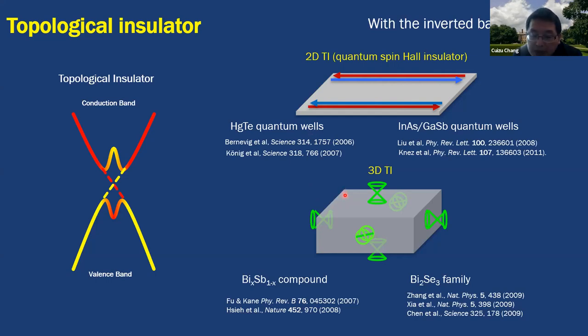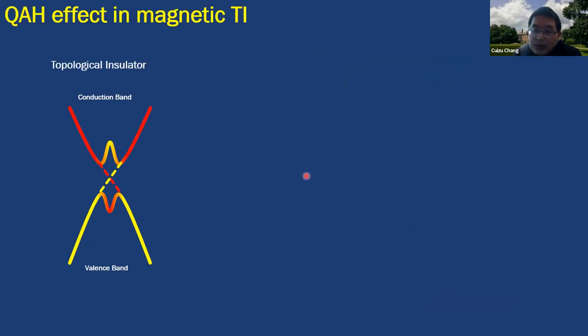And a 3D topological insulator was first discovered in the bismuth antimony alloys, and also in the bismuth selenide family materials. And later there are a lot of these 3D topological insulators. So in my experiment, we mainly talk about the bismuth selenide family topological insulators. So now, as I just showed you, the topological insulator satisfies the first condition for the quantum anomalous Hall effect. And the second condition is we need to make the material become a ferromagnetic insulator.